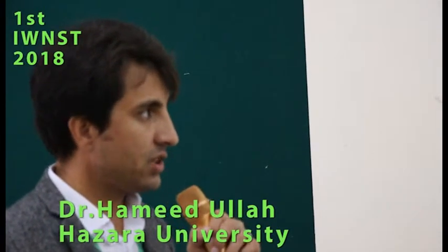So then we tested a new material, preparing hollow spheres of the transition metal fluorides. Here we tested nickel fluoride, and a 3-step method was used. A solid template was coated to make a core-shell structure, and then the core was removed. This is a very specific process, fluorination under 100% pure fluorine. The silicon dioxide reacts with fluorine, giving you a gas, while you get the anhydrous transition metal fluoride hollow sphere.